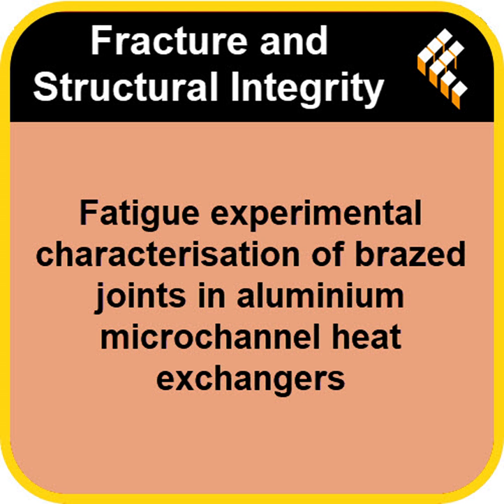That's the surprising part. The extruded tube material, which has a different starting microstructure, more fibrous, already strain hardened from the extrusion process itself, just reacted differently. How? For this particular alloy and structure, the heating cycle seems to have actually stabilized the microstructure. There might be some diffusion effects, maybe some precipitation phenomena happening on a tiny scale. Meaning trace elements moving around and pinning things? Yeah. Sort of like that. Hardening the matrix slightly. The bottom line is, it showed a modest but definitely measurable increase in strength after going through the thermal cycle. That is hugely relevant for anyone designing these things.